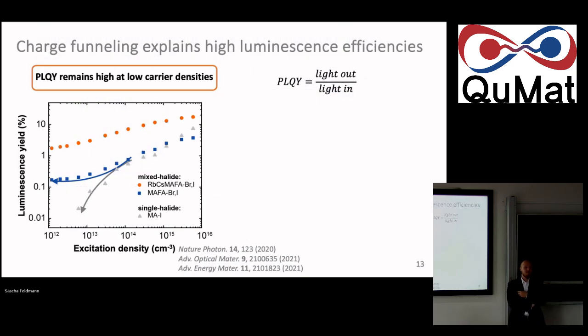So yeah, you can ask what does that do to your actual performance, because I opened up with saying we want to work on making solar cells and LEDs better. Well, a very good proxy of that to start with is something we call photoluminescence quantum efficiency or quantum yield, PLQY, which sounds fancy and just means the amount of light out divided by photons you excite the material with. Say 10 photons in, 8 photons come back out, 80% efficiency, fantastic. So we do this, but now we make it a measurement as a function of the excitation density, how hard we're exciting such a film.